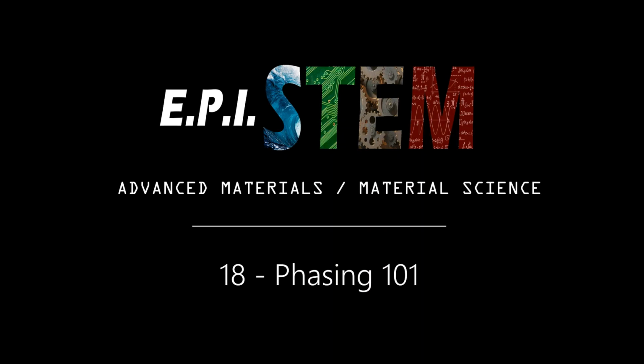Solid to liquid phase changes are the ones that are most widely used within the world of phase change material technology. So the way that you typically prepare one of these pieces of technology is by filling a porous material with the phase change material, or a PCM. You can use carbon nanotubes, which have a lot of useful properties. There are plastics that are porous. You can use metal organic frameworks. Yep, we're bringing metal organic frameworks back into it. There's a lot of different properties that you can tune for. And again, we'll see those later when we start talking about some of the applications.